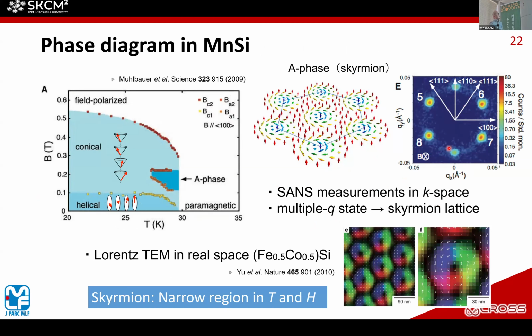Okay, then here is the magnetic field versus temperature phase diagram of manganese silicide. As you can see, below the transition temperature, it becomes a helical structure. It's kind of a spiral magnetic structure. And when we apply a magnetic field, this spiral changes to the conical structure, because the magnetic moment tends to align along the applied magnetic field direction. And when we apply more and more field, finally the magnetic moment aligns along the applied magnetic field. Then the system becomes a forced ferromagnetic state.